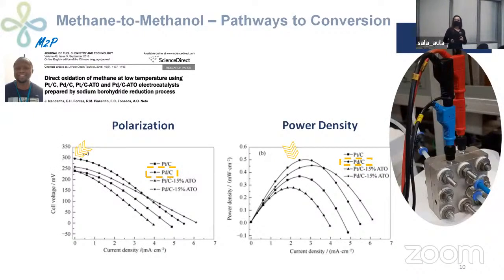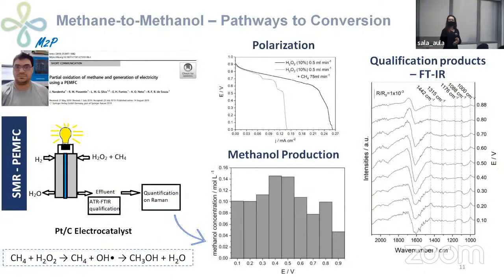So furthermore, we have the polarization curves and the power density, and we observe that the palladium electrocatalyst results in the higher open circuit potential and the higher power density. So, in view of these results, we replaced the use of hydrogen peroxide together with methane in the reactor and analyzed the products formed by quantification with Raman and qualification using the infrared spectrum.